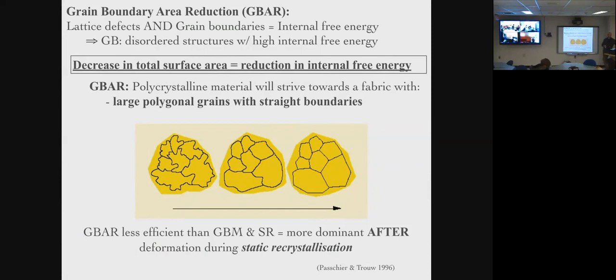Okay? This is called static recrystallization, and it occurs in pretty much any kind of mineral if you have sufficient heat to activate diffusion processes without deformation. So dislocations are not migrating through the crystal lattice. You're in fact reducing the internal energy state of your crystal by bringing the grain boundaries into a stable 120-degree configuration. Okay? So if you pour your beer really fast in a glass and take your hand lens and look at the foam, you'll see these bubbles forming much larger with time. That's a perfect example of essentially reconfiguring your bubbles in your beer foam into a stable 120-degree configuration.